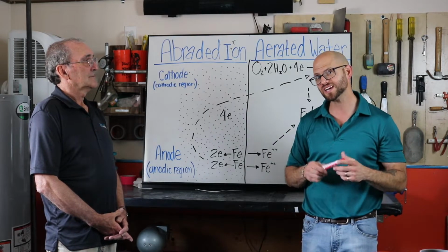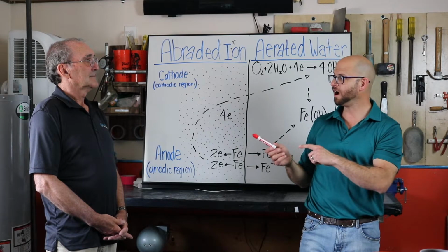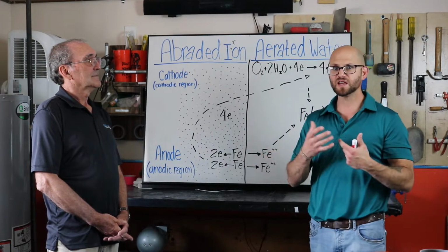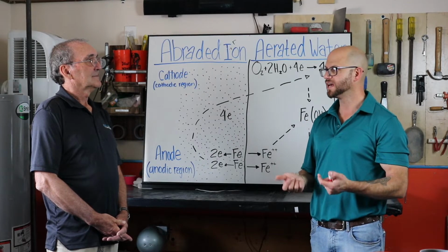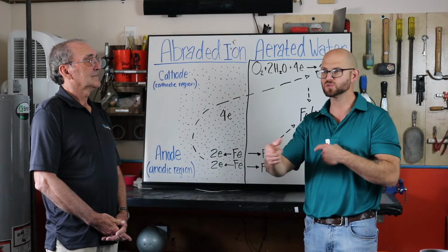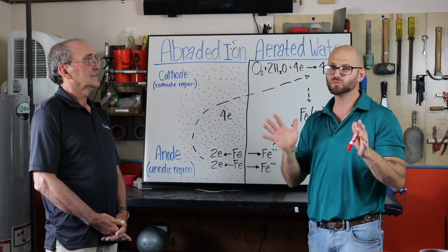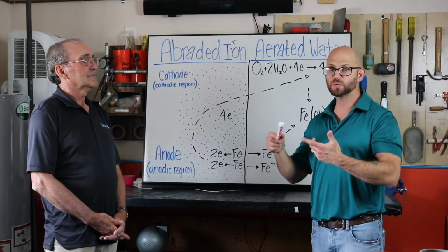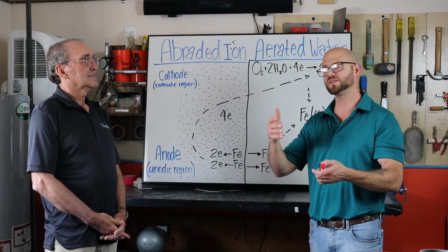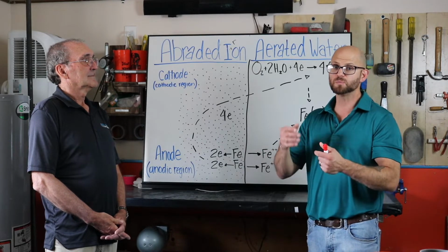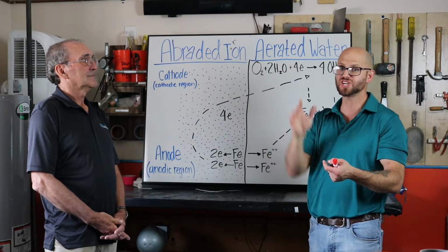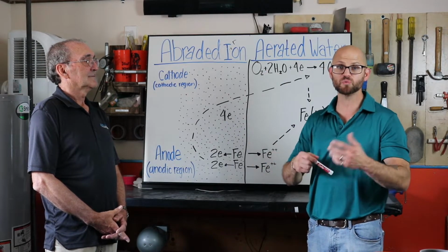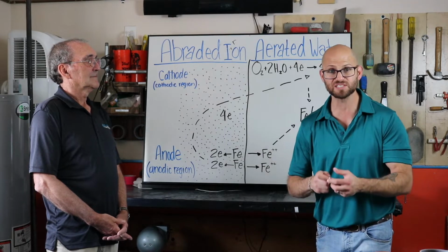Now in concrete, it changes. Because within good concrete, once that rust happens, that rust acts as a protective coating. And as long as we don't have the migration of electrons or pore water, that rust won't really continue. And that's the unfortunate reality, especially when we have subpar concrete, if there's too much water, if there was cracking. With too much water, we create those bleed channels that can go all the way down to our reinforcement. That allows the migration of water and salts that can exacerbate that steel corrosion.